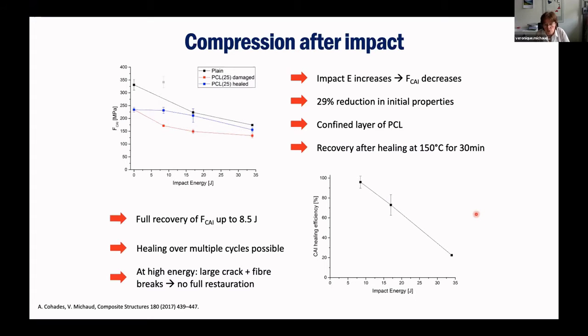So we saw also that over multiple cycles, it was possible to heal. And we saw that at high energy, we had large cracks and fiber breaks, so then we could not restore. But we still managed to do a publication on this. It was in 2017 again.